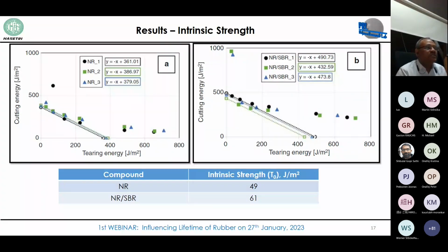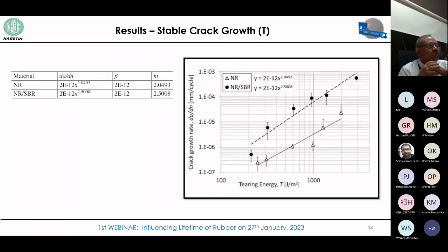And SBR is in between. And these results are also in line with that observation as well. So this is the stable crack growth zone, crack growth graph for these two compounds, NR and NR SBR compounds.